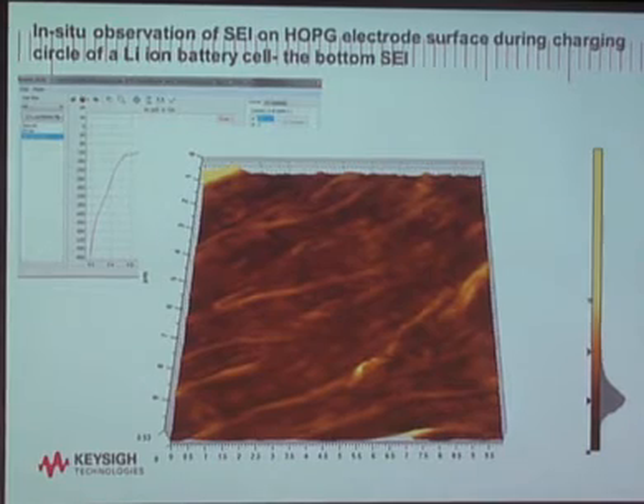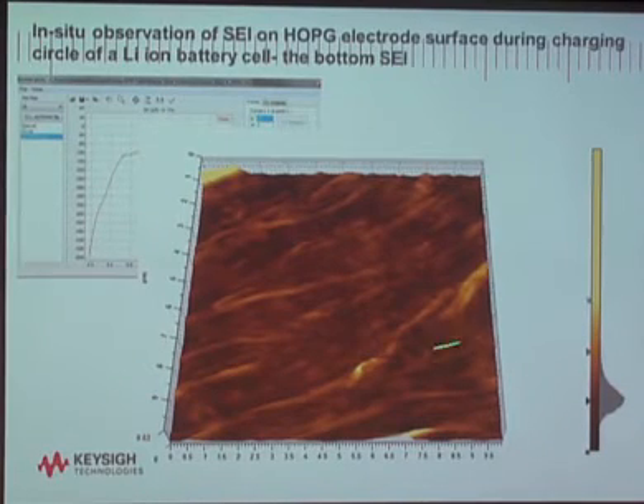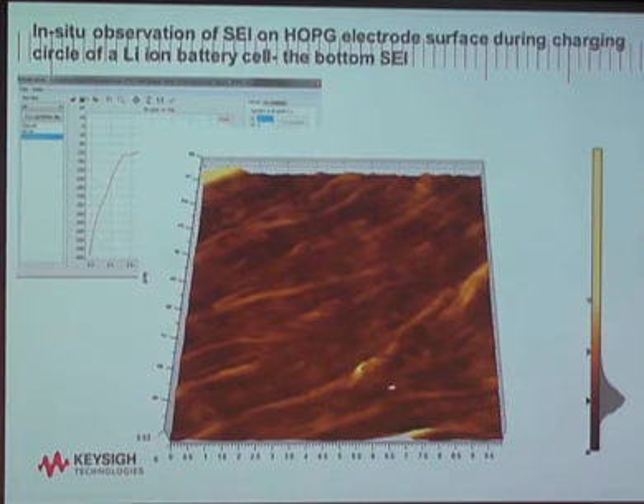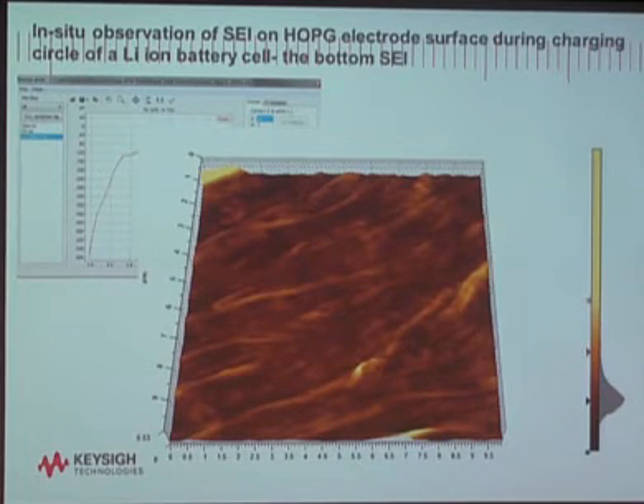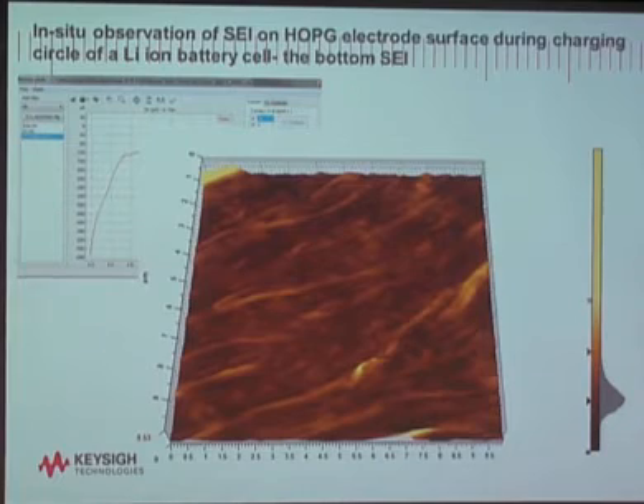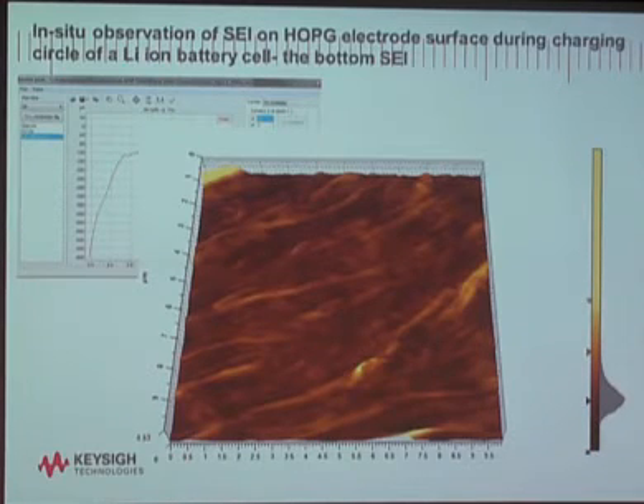Now, we use a little bit more force and remove the first layer, and we look at the second layer. It has a very unique, distinct look. It's very interesting. What does it remind you of? It reminds you of a bed sheet, a wrinkled bed sheet. And what that tells us is that maybe it's possible that the lithium not only inserted underneath the graphite, but also inserted in the crystal structure of graphite and caused it to swell and expand laterally. That's what the wrinkled sheet tells us. And the next thing we did, we applied a little bit higher force in this little square to see if we can push it down.